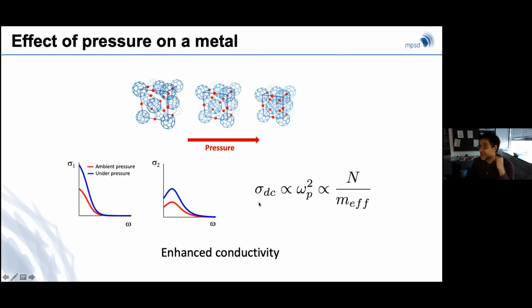The reason for this is that sigma dc in a metal basically scales with the effective mass and the carrier density, which are both quantities that become more favorable as I apply pressure. In other words, sigma dc depends on the square of the plasma frequency, which shifts to the blue as I apply pressure or as I reduce the effective mass.